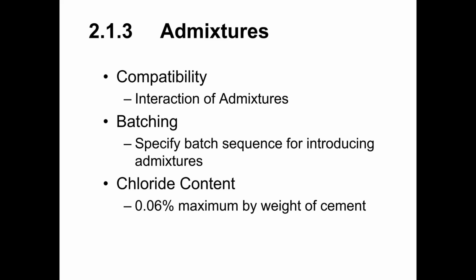For pre-stressed concrete, this is especially important because high strength steel that is under a sustained stress is more susceptible to corrosion. And with pre-stressed concrete, that's exactly what we've got. We've got high strength tendons that are under a sustained tensile load. And so due to that increased potential for corrosion, for pre-stressed concrete, the chloride content is limited to 0.06% max by weight of cement. For non-pre-stressed concrete, the chloride content is still limited, but it is a much more liberal limitation than for pre-stressed concrete.